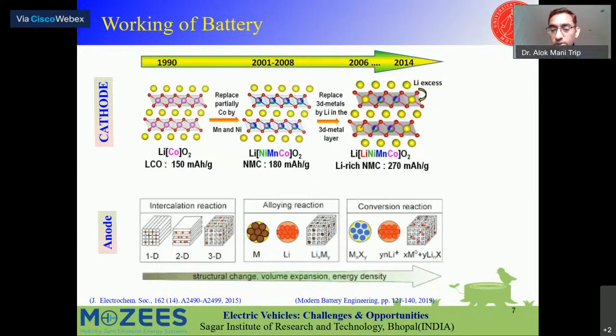And the basic difference between these two anode materials is that the graphite one is based on intercalation, because the ions go into the layers of atoms and get intercalated, while the other two are doing direct electrochemical reactions with those metals or non-metals, and then when they react, they will go into a different phase. If they go into a different phase, they definitely increase the lattice size. If lattice size increases, then the overall material starts breathing. Breathing means expansion, like our lungs expanding when we breathe in.